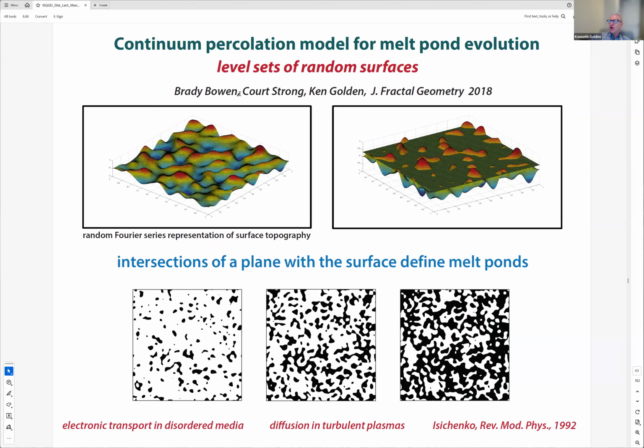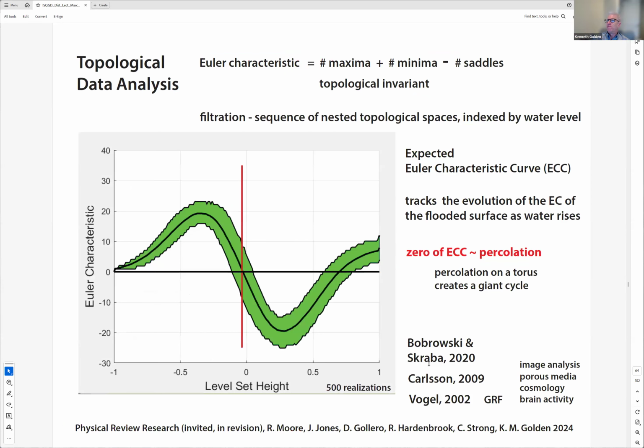And again, one of the simplest initial models that really does a good job is this: here's the surface topography of the ice, and then we look at the level sets, intersecting the surface of the ice with a horizontal plane and then moving that plane up and down. As the plane moves up, the ponds grow and become more complex. And indeed, we get a nice match for the fractal dimension transition from this model.